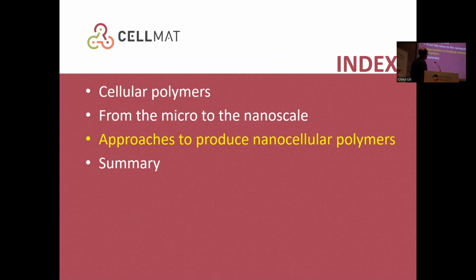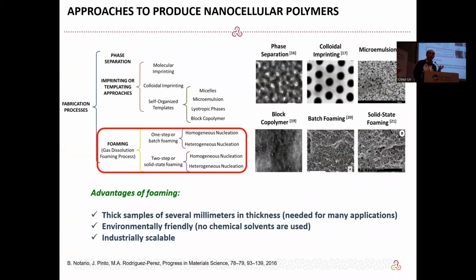So I will speak briefly about how to produce nanocellular materials. Nanocellular polymers are known and have been produced by different methods: phase separation, imprinting, templating approaches. That is nice, and this has been done before. The main issue of these methods is that typically the thickness of the sample you produce is very small, and typically you use chemical solvents. As we want to produce, for instance, a thermal insulator to substitute a window, so remove the silica of the window and put our nanocellular PMMA, we need some thickness. We need maybe 4 millimeters, 10 millimeters, 2 millimeters, so those approaches are not what we want.